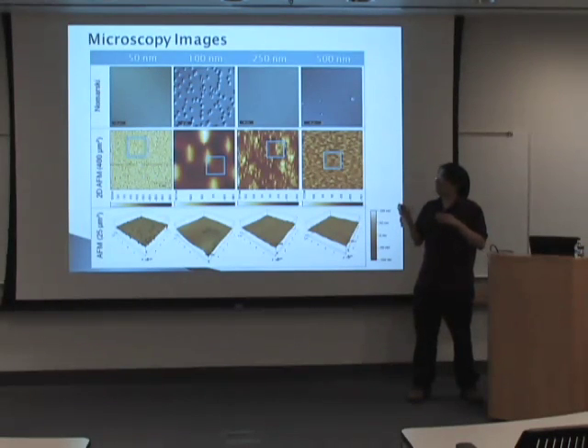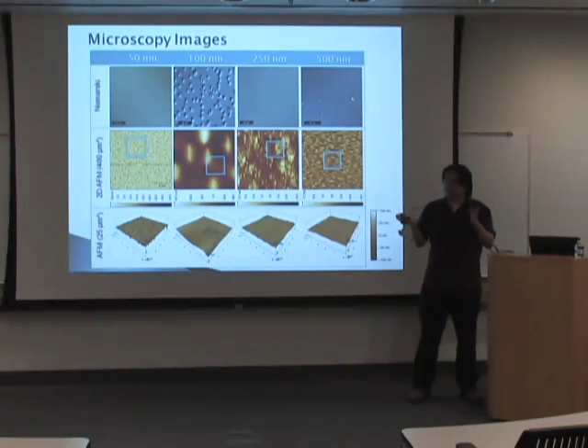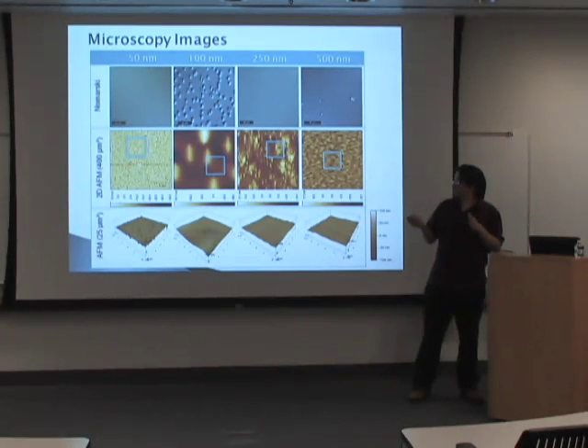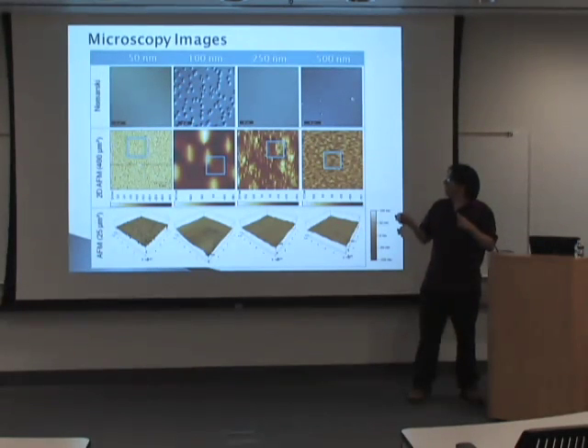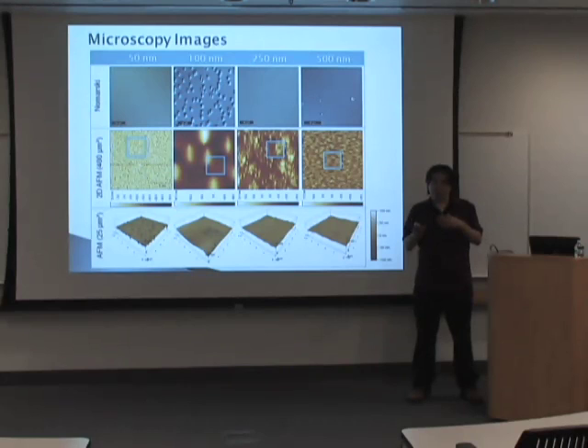But you can also see these mounds in the next series of the AFM. So at least what we're seeing is real and not artifact, and that tells us the rest is also real. We do see these textures on them, and these textures correlate to roughness. And the more interesting one, at least in my opinion, is the 3D images.